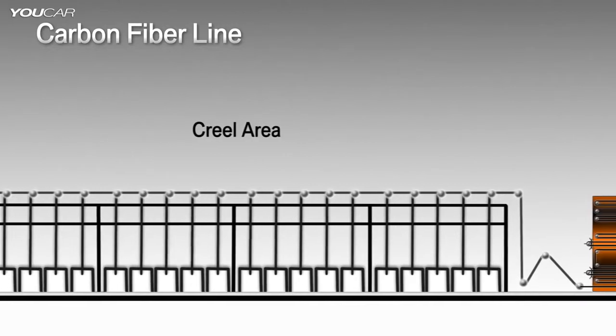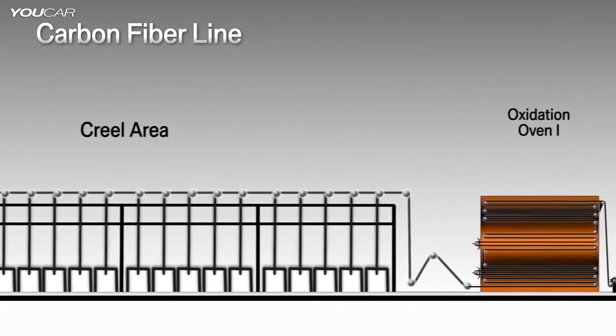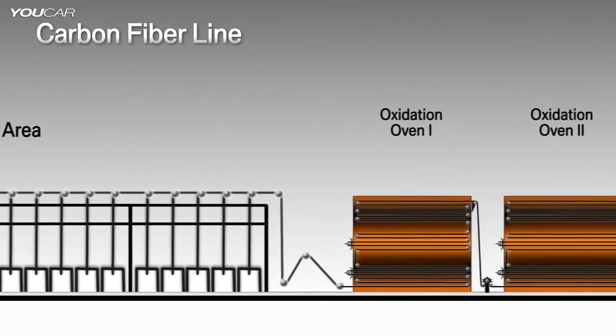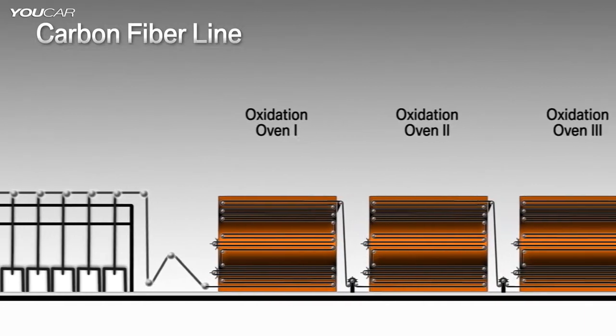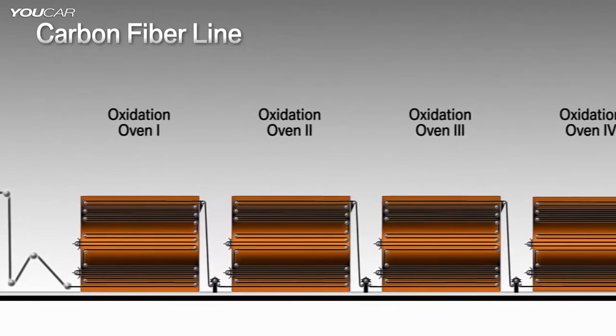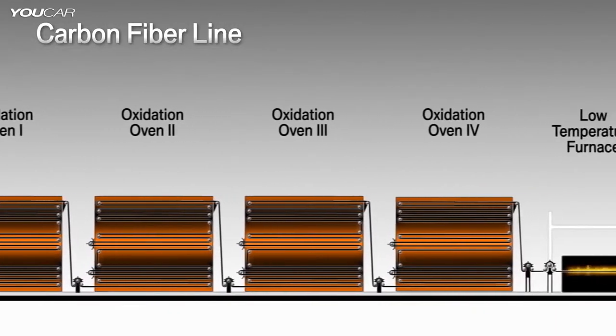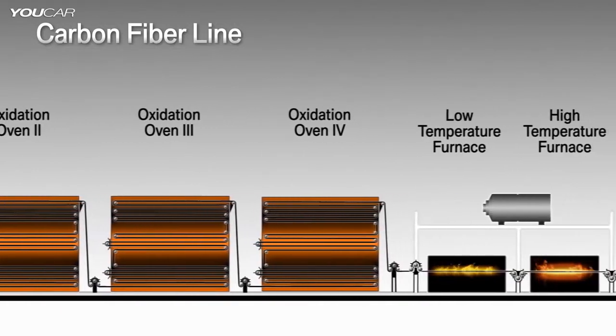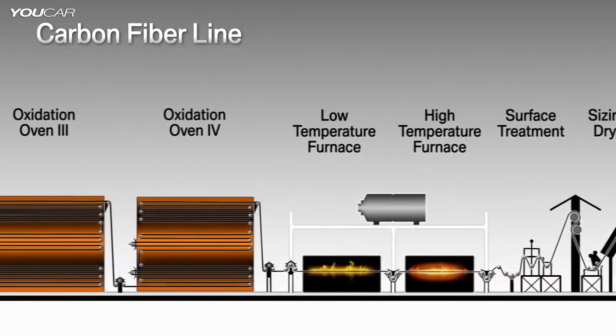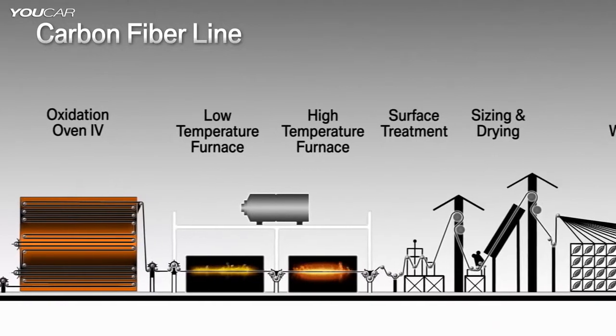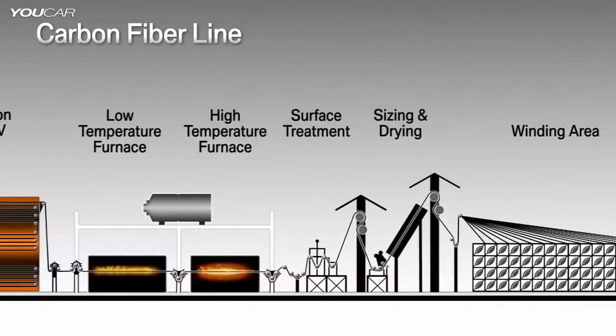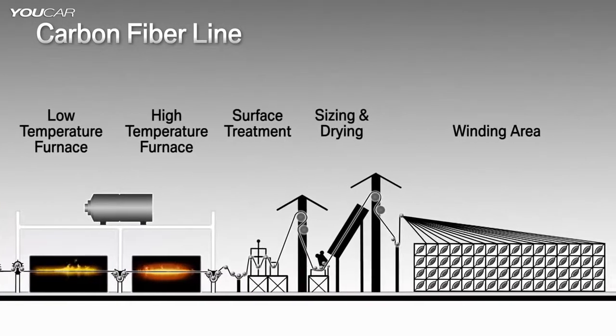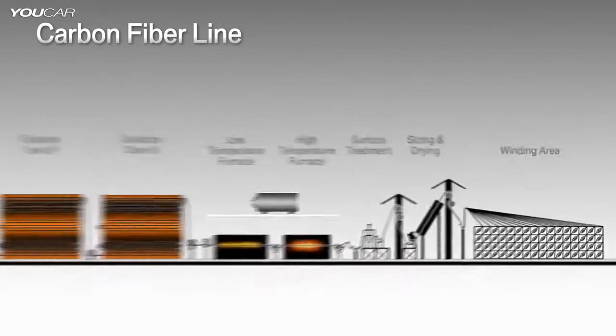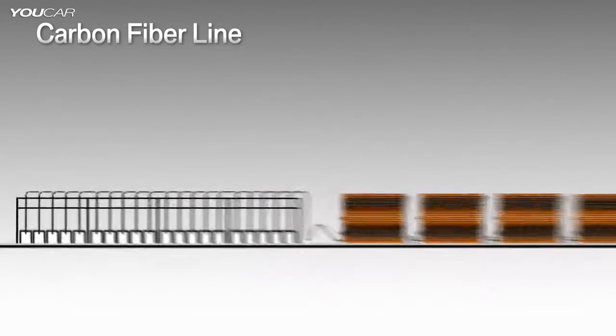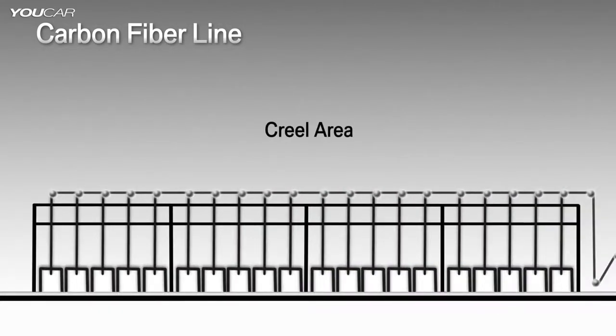This is a complicated production process in which the fibers are heated in huge ovens until they are black, strong, and light. The huge furnaces reach temperatures of up to 1,400 degrees Celsius. The fibers are spun into fine threads and rolled onto spools for shipping to Germany. The basic material required for manufacturing carbon fibers is a white polyacrylic thread, the so-called precursor.